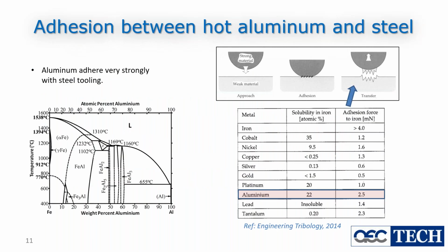Okay, this is some experiments done using a hard ball touching the surface of the softer material, and they push it with some force to make some deformation in the soft material with the hard material. So in this case, the hard material is iron, and the soft material can be different metals. And it's showing how much force is needed to rupture that adhesion that has been between the hard, strong material and the weak material.